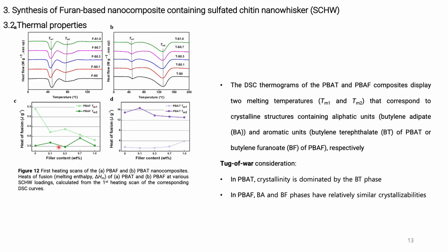The difference in the multi-phase structure of the two types of nanocomposites is understood by considering the tug of war between the BF and BT units against the BA units for crystallization dominance. While the pi-pi stacking of benzene rings facilitates the formation of aromatic BT crystallized phases, the furan ring distortion impedes the crystallization of aromatic BF units. So, also by examining the changes in the heat of fusion, we can investigate the influence of SCHW on the microstructure of the polymer matrix.